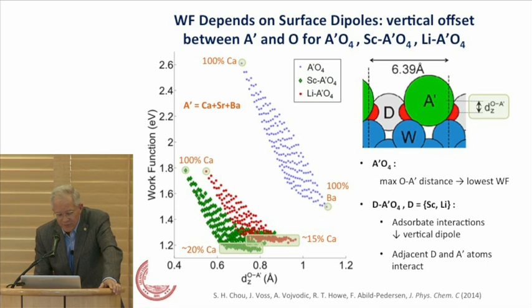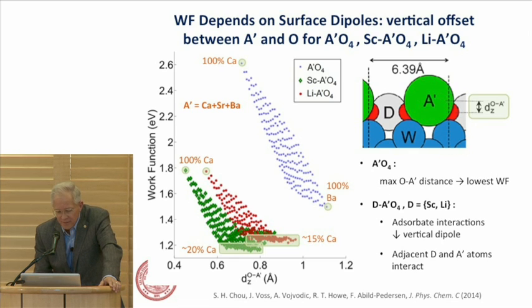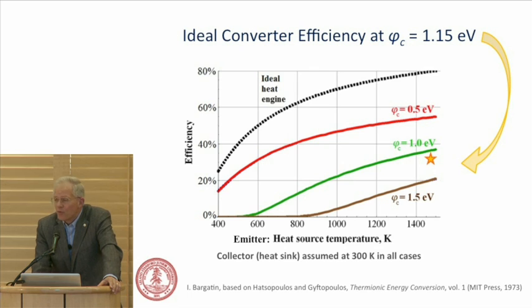Work function is a function of the effective offset of this synthetic atom from the oxygen at the surface. And in fact, that could be a physical insight in how you can control the work function. So in any case, where are we? Okay, this was shown earlier.